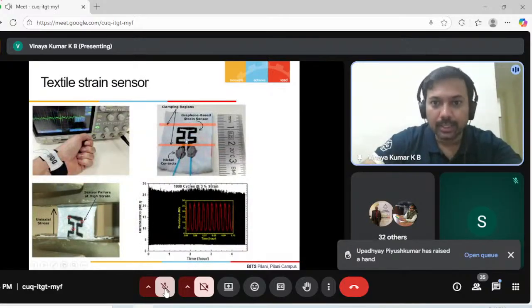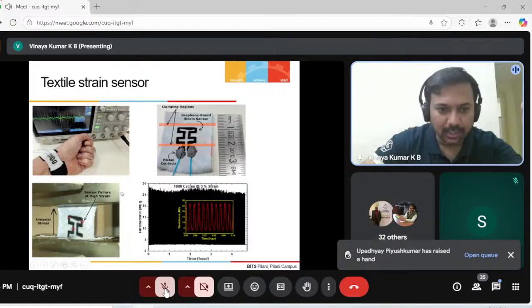Using carbon inks and graphene ink, we were able to produce a strain sensor. Using the strain sensor, we were also able to measure the heart rate. As you can see, the sensor printed on a textile using a nickel contact is good up to 1000 cycles at 3% strain. The results are very repetitive. The sensor failure test happened after several uniaxial stresses were applied, much more than 3% strain.